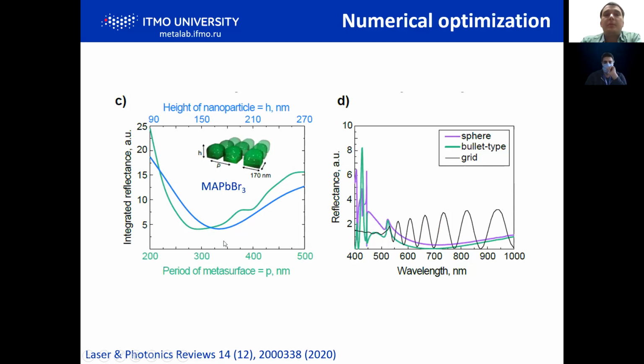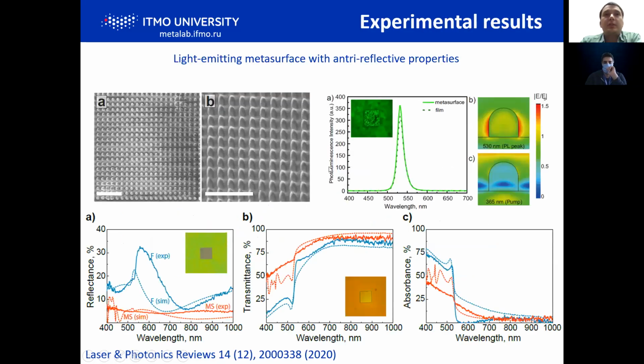And we see that at certain parameters, at a height around 160 and a sub-wavelength period for the visible range, we achieve a minimum in reflectance. So here, this is for bullet-type particles, and you see that we can achieve very low broadband reflectance from these films. So the experimental results are here. We fabricated arrays of these perovskite bullet-like nanoparticles, and you see that the reflectance from the film is up to 30%, and after nanostructuring we have only around 5% of reflection and an increase of transmittance through such a metasurface. So it means that we suppress backward scattering from each meta-atom and achieve anti-reflection from this metasurface.